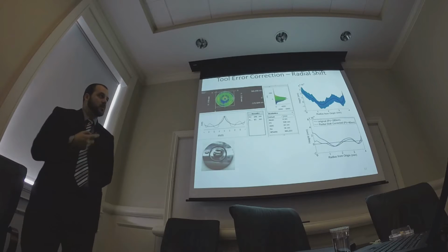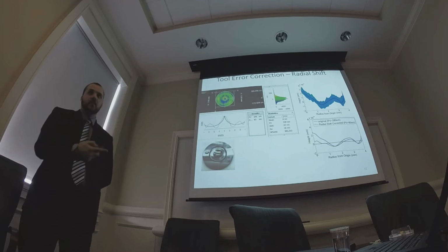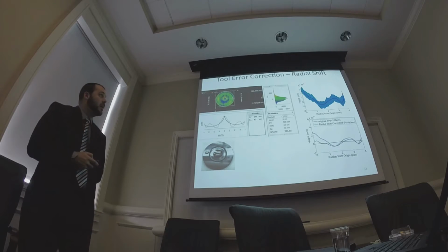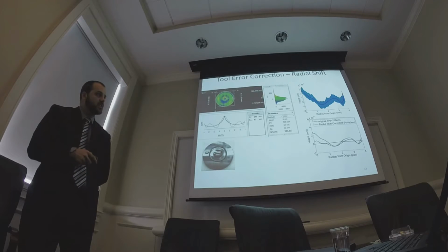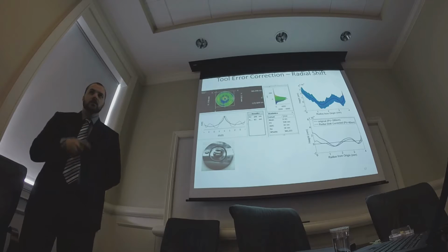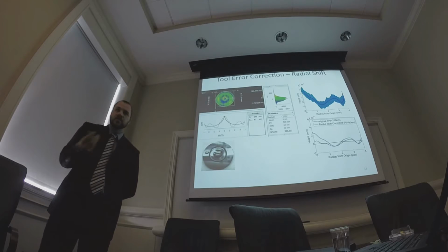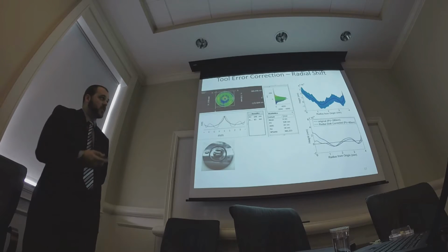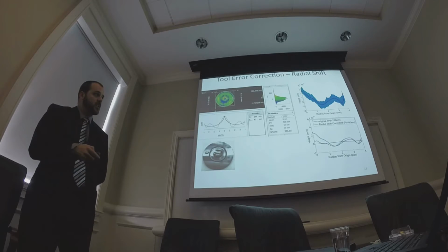So now we need to correct both of them. Independent is the wrong word, but we correct them one at a time, we optimize for one and then correct the other. So if we take the blue line as our original, the green line is after we remove the error from tool position, the diamond tool position. We've corrected for the radial shift and we get the green, that's the residual.